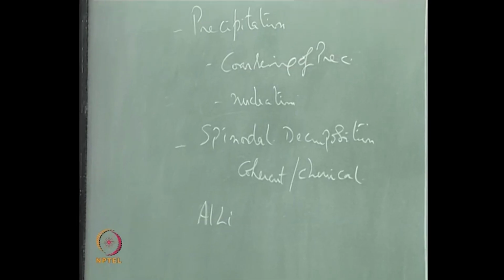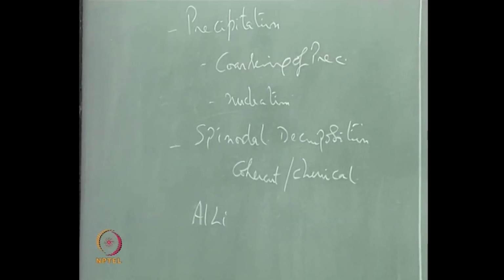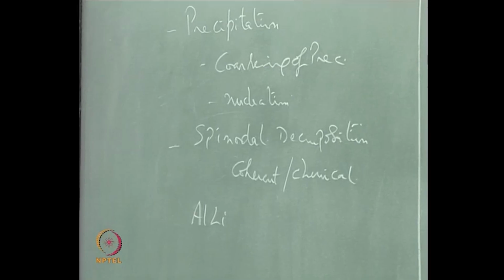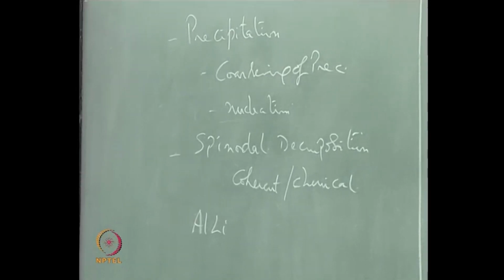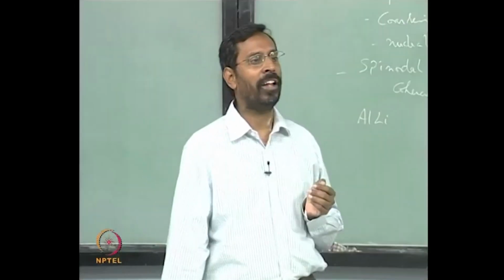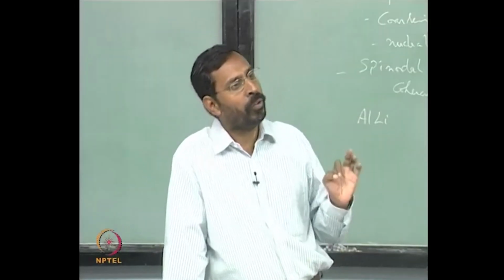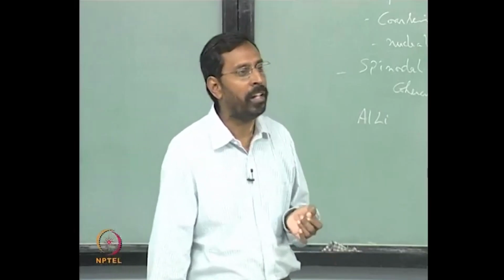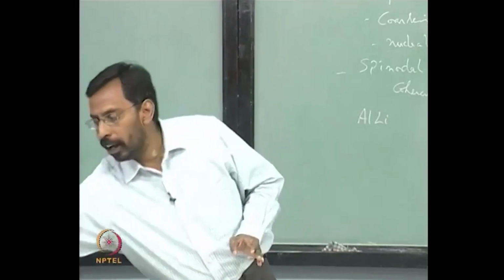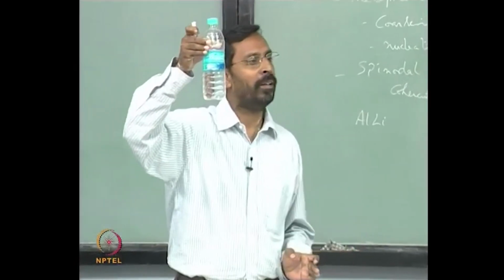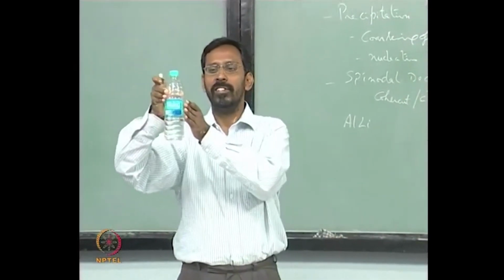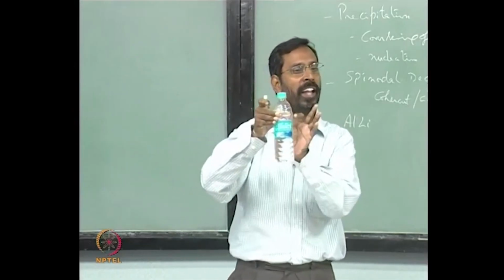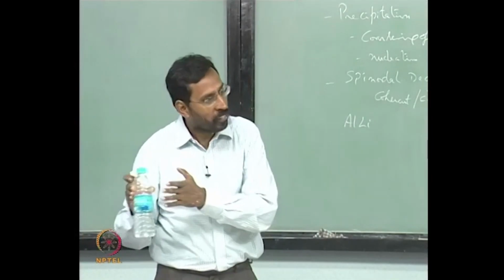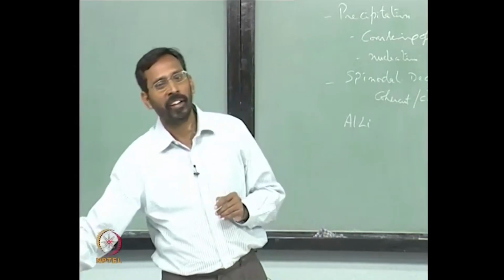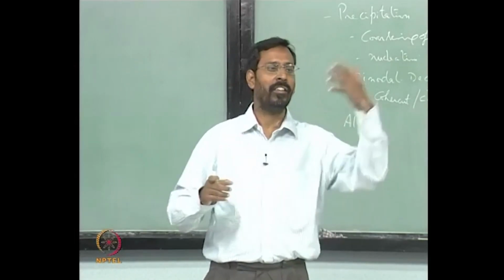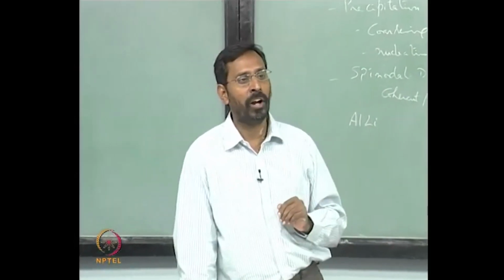Handling lithium is not easy. You cannot simply keep lithium outside in the atmosphere. So that is one. But once you put it inside the aluminum, you make an alloy out of it. Even after the alloy is made, lithium has a tendency to diffuse out, being a smaller element. So if you take an alloy rod like this aluminum lithium rod, after a month the surface concentration of lithium is going to be higher than the concentration inside. So it has diffused to the surface, and once it diffuses to the surface, there is a possibility that it can react with the environment.